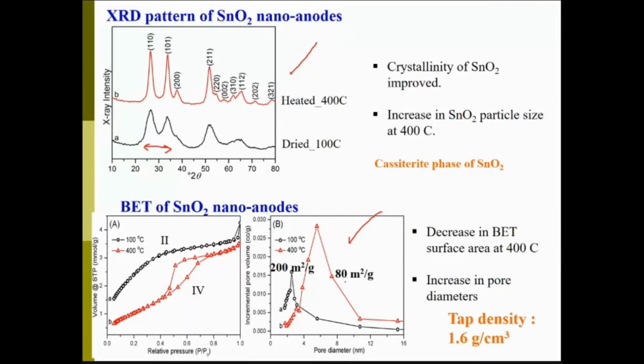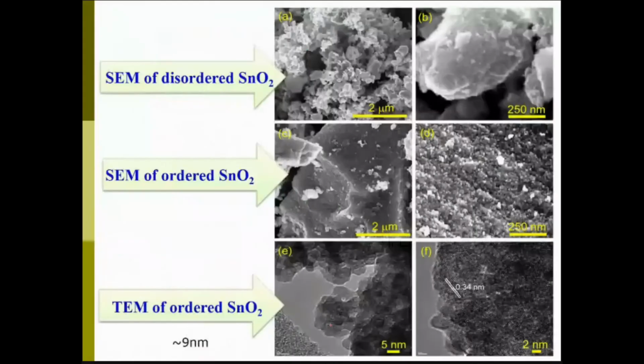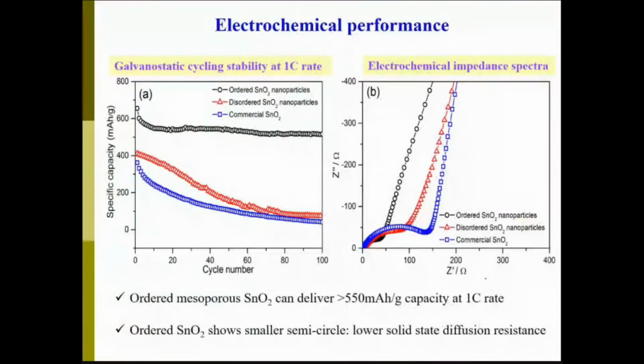Here, the take-home message is, when you have the material only gently dried at 100 degrees Celsius, the surface area was high. As you heat it up to 400 degrees Celsius, the surface area goes down, but there are cavities generated around 4 to 8 nanometers, and those cavities were very important for us to expand the material. This is a scanning electron microscopy picture where you can see those particles are accumulated. They are very tiny in size. That is going to give you the property.